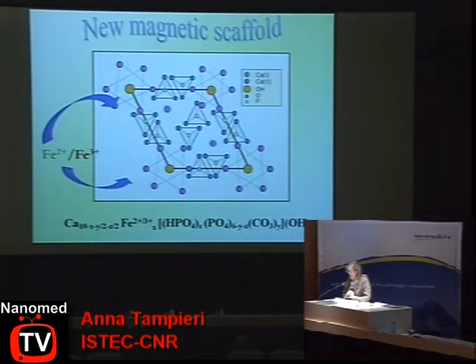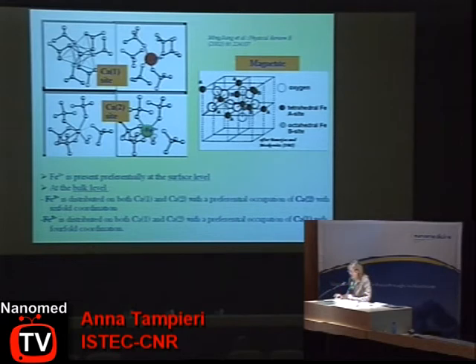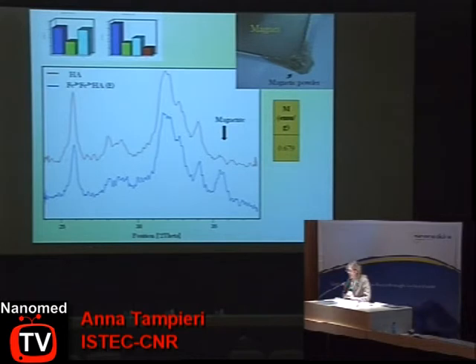We decided also to try to produce the same scaffold with superparamagnetic ability. Actually, we can introduce into the hydroxyapatite lattice many different doping ions, because of the specific microporosity of the cell of hydroxyapatite. So we decided to introduce iron ions. And since we have two positions of calcium, which are structurally different, we decided to try to introduce into the apatite itself superparamagnetic domains very similar to what you can find in magnetite. So we have to introduce iron 3+ and iron 2+ in a specific ratio and with a specific coordination. We succeeded in that, and at the end we are able to produce an iron-doped hydroxyapatite, minimizing the formation of magnetite to 1% maximum.